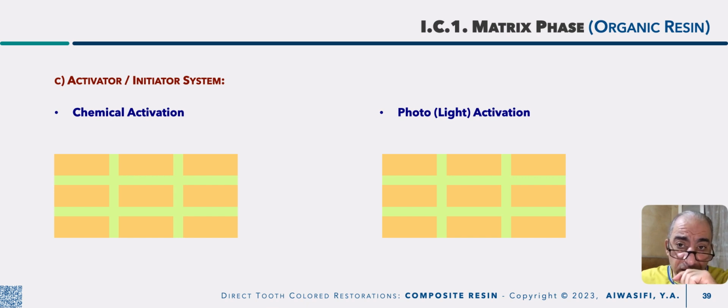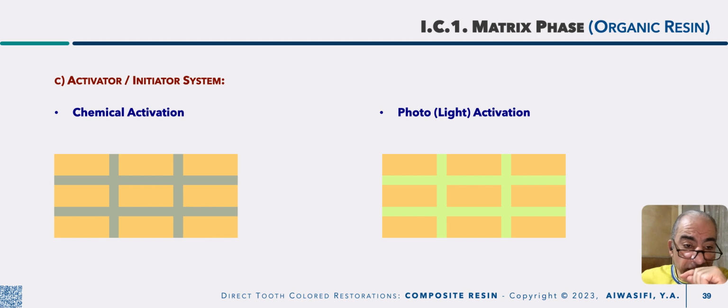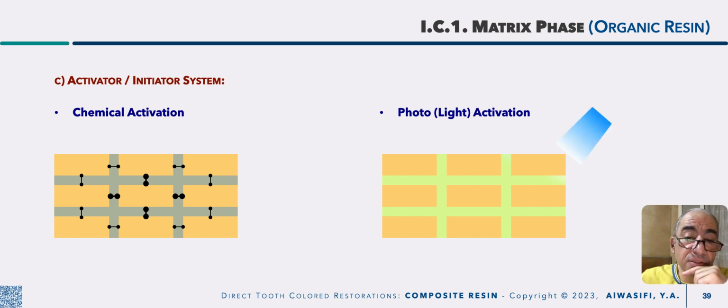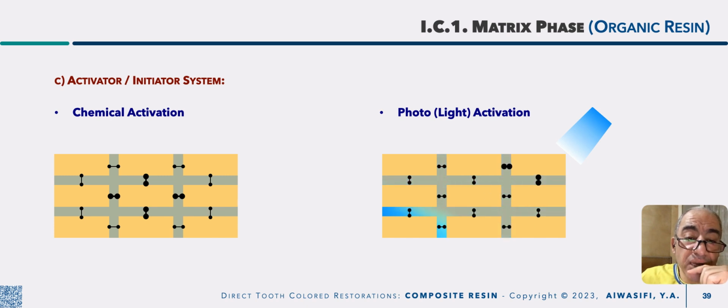Another difference regards the polymerization shrinkage and its direction. Composite starts the reaction at the site of maximum initiation, or at the site starting the initiation. For chemical cured, once you mix them, the maximum initiation will be in the center of the material, while for light activated, the first site to be initiated is the one near the light.